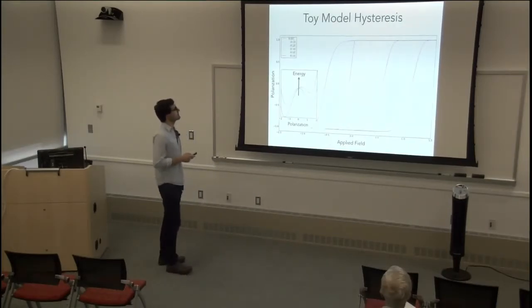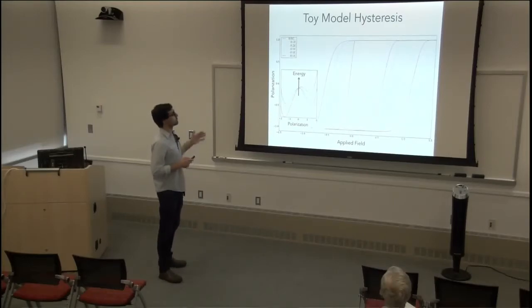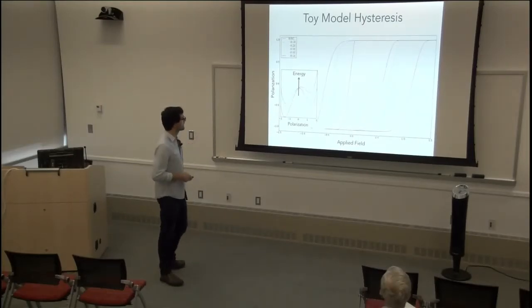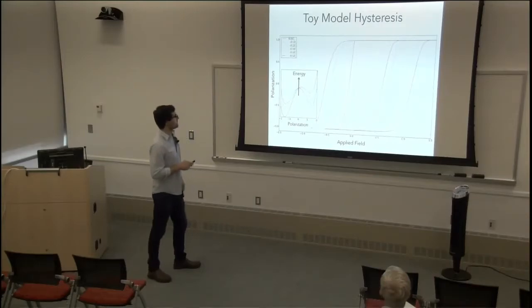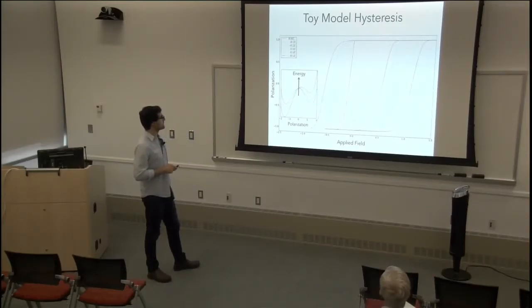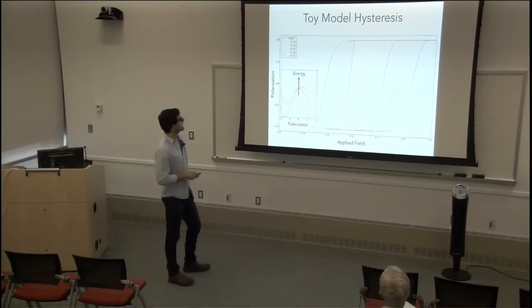non-equilibrium dynamics. So what we do is create a toy model hysteresis. Here in the inset, I want you to focus on the inset first. This is energy versus polarization. And I start with this purple here, which is your symmetric double well. And in the big plot, which is polarization versus applied field, which is your hysteresis, you get a symmetric hysteresis.